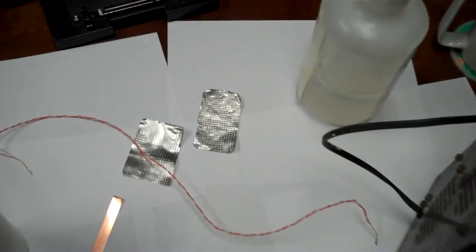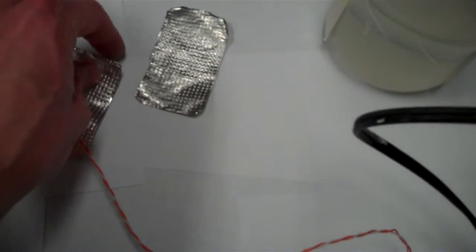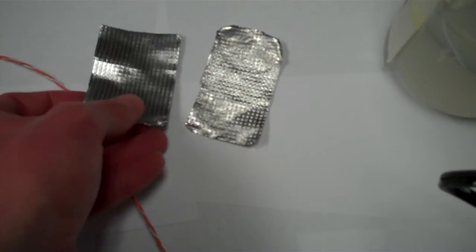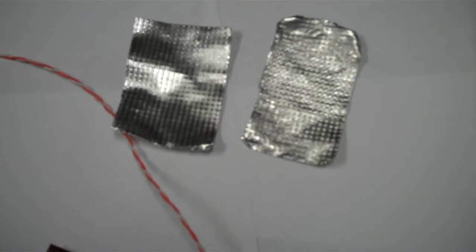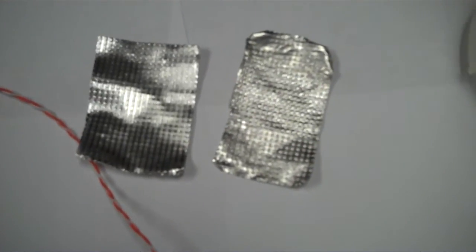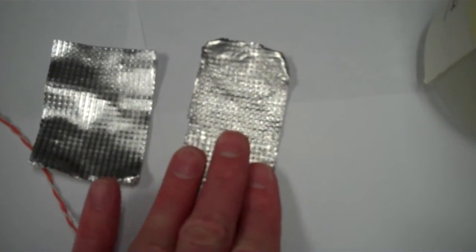Now, as I mentioned, the use of soluble indium anodes, I do consider the use of soluble indium anodes a necessity. Otherwise, the indium metal content of the bath will get out of whack and it will stop plating properly.